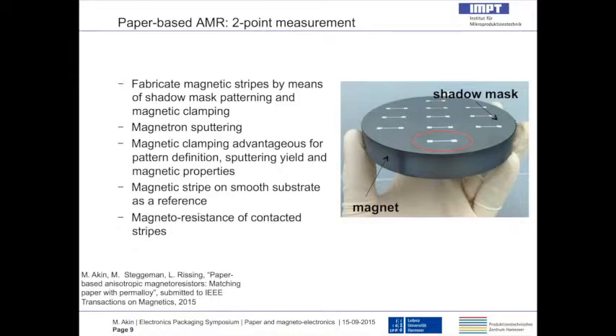And we fabricate those samples in the shape of a magnetic stripe, because the magnetic stripe gives the direction of the electric current once applied on it, and therefore I would know how the electrons are flowing, in which direction they are flowing. And we fabricate these stripes by means of shadow mask patterning, because it's the easiest thing. However, we are working on photolithography on paper, and we use a magnetic clamping to have a highly defined shadow mask contact to the paper and a highly defined pattern transfer or pattern formation of the coating. We use that with a combination of magnetron sputtering. And I forgot to mention that in the first set of experiments, we used also the same technique to coat those papers.